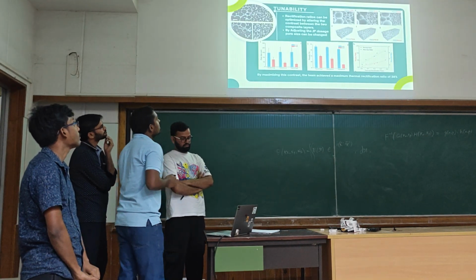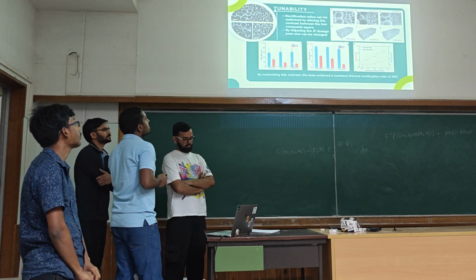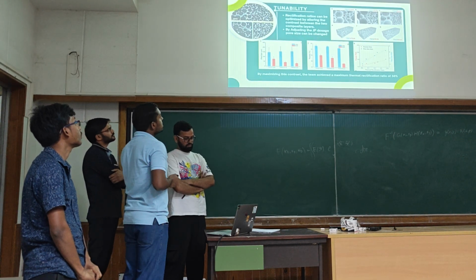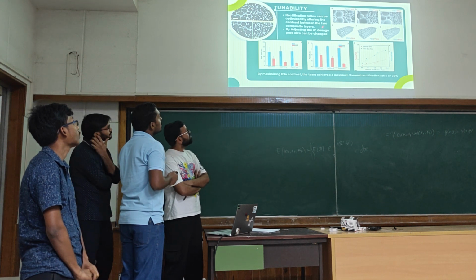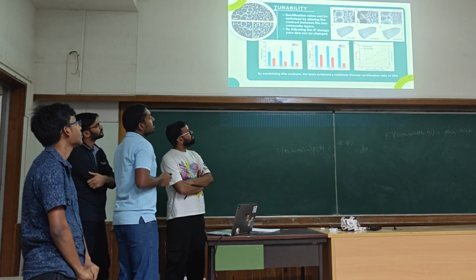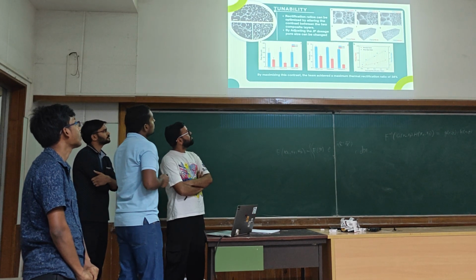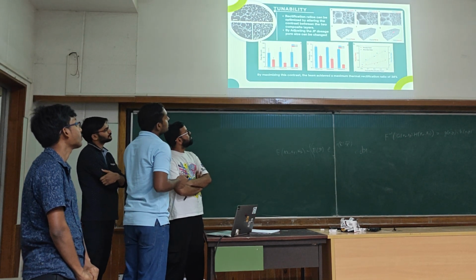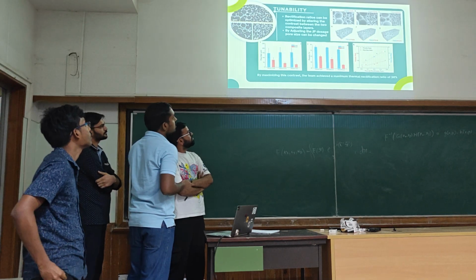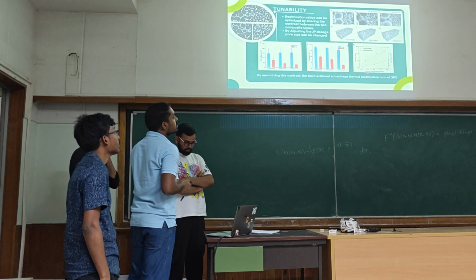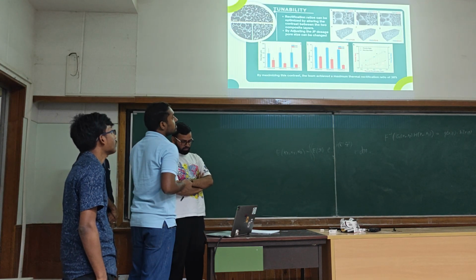So basically, we can optimize it based on our needs. We can change the pore size, or we can change the porosity, depending upon the requirement. Here there are three different combinations of pore size and porosity, and as we can see from here, as the porosity ratio increases, so does the thermal rectification ratio.